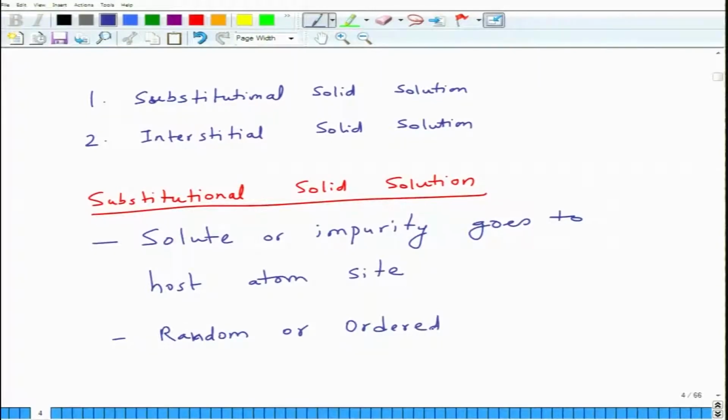So this will be determined by various factors. For example, thermodynamics plays an important role. The entropy of substitution, configurational entropy will play an important role in determining where we'll go, and temperature plays a very important role. So it's a combination of enthalpy and entropy and temperature which will determine the free energy of which structure will be minimum.